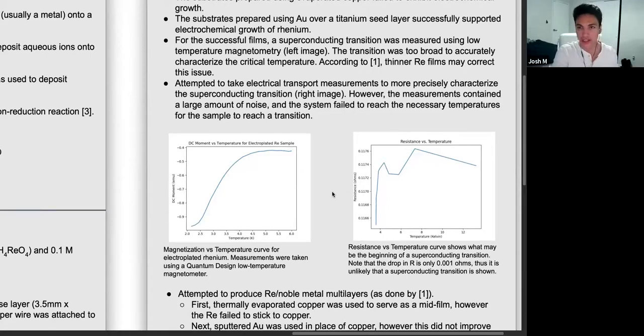So we wanted to get a better idea of what was happening. So we went to an electrical transport measurement, and that's shown here on the right. Unfortunately, our setup for this measurement was really noisy and couldn't quite get down to the temperatures we needed to see the transition. On the right here, it looks like we might be reaching a transition point. However, if you look at the scale, you can see that it only really drops about 0.001 ohms, which is definitely not sufficient to conclude that it's a superconducting transition.